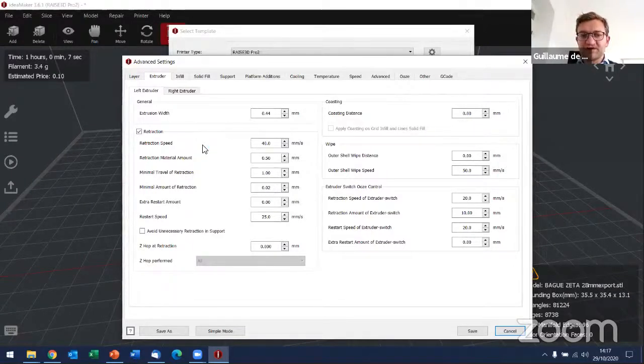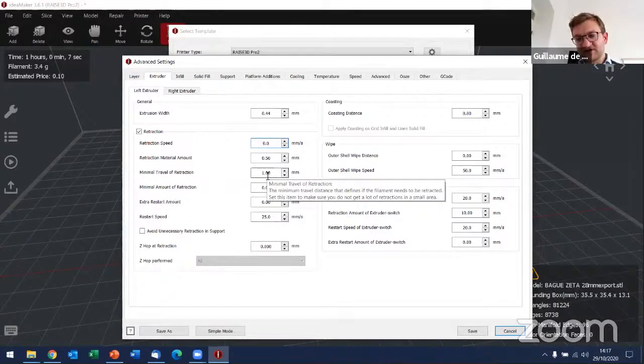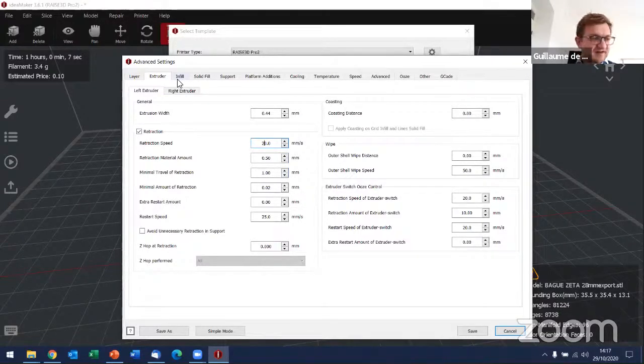So we usually put retraction, but this is something quite critical with ceramic and metal filaments, because ceramic and metal filaments are quite brittle, and you want to avoid being too hard with them. So we usually put retraction, but we will decrease the speed of retraction. That's all. We'll put a relatively slow speed. That's it for this tab. So here are again two important parameters: extrusion width and retraction.